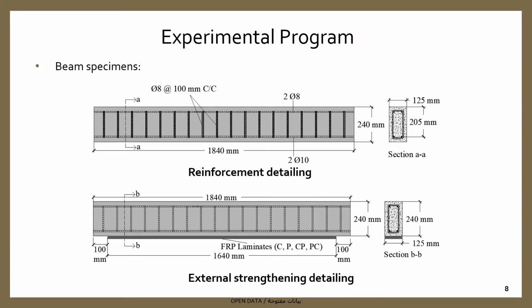Moving to the experimental program. The experimental program in this research was divided into two stages, which are coupon tensile tests for all the strengthening schemes and flexural tests for all the beams. A total of 5 beams with a length of 1840 mm, a depth of 240 mm, and a width of 125 mm were tested. The effective depth of the specimens is 205 mm.